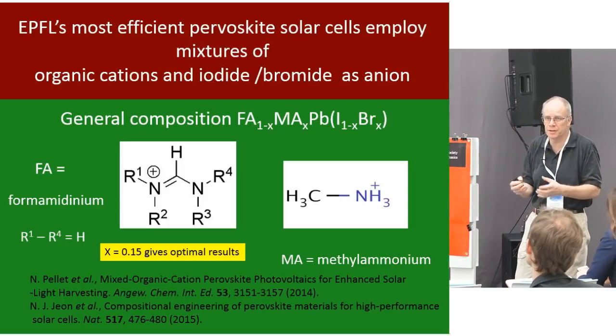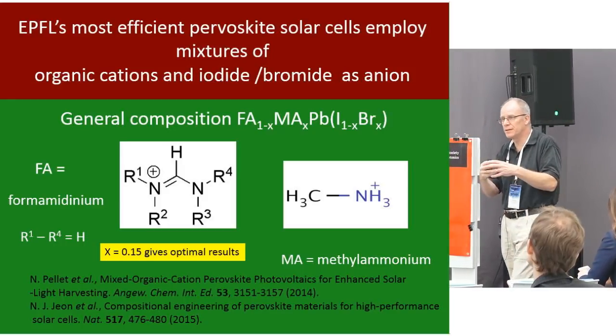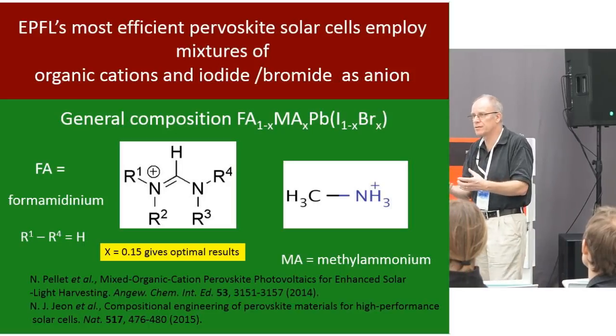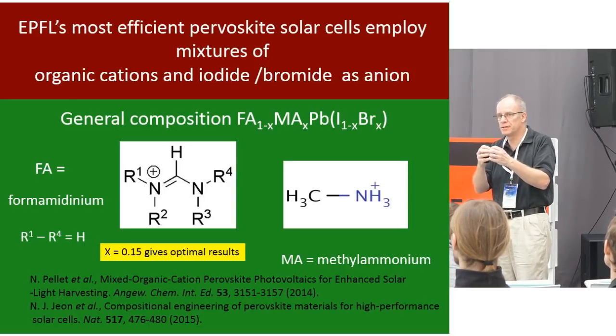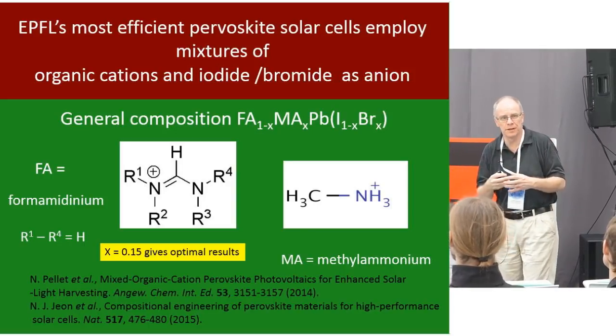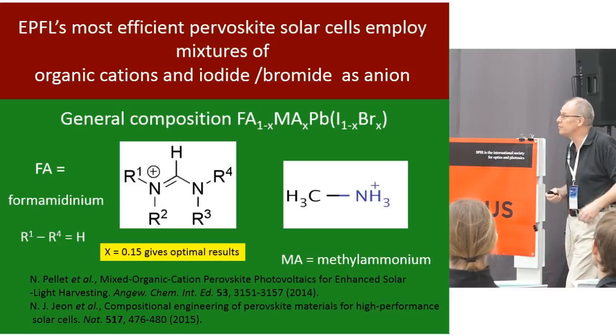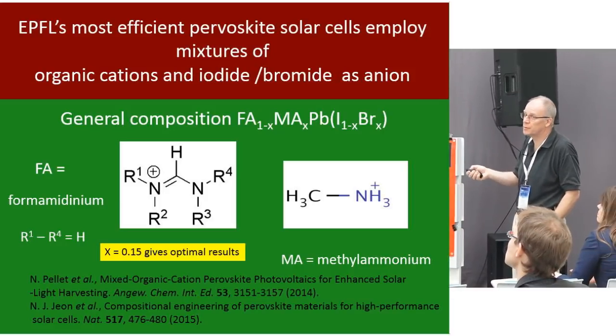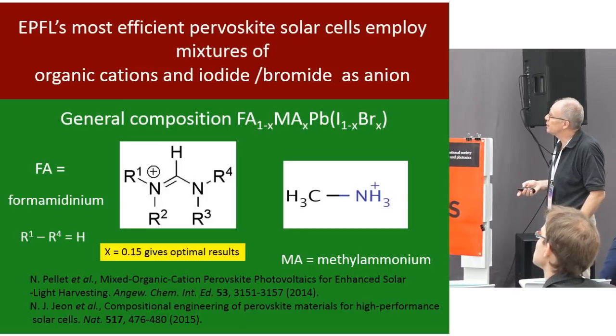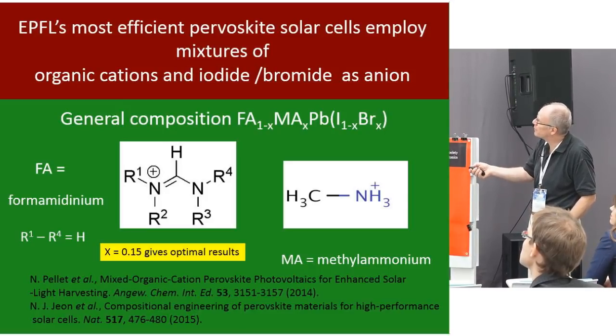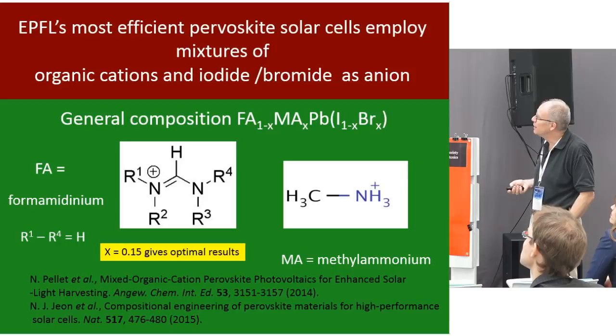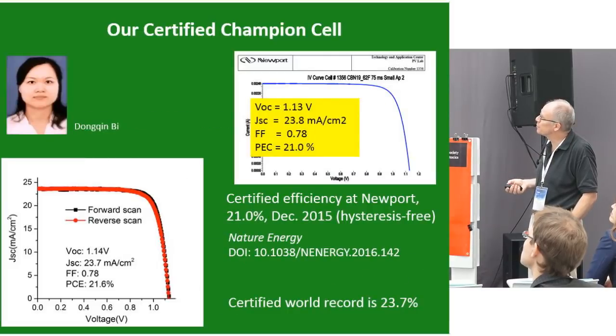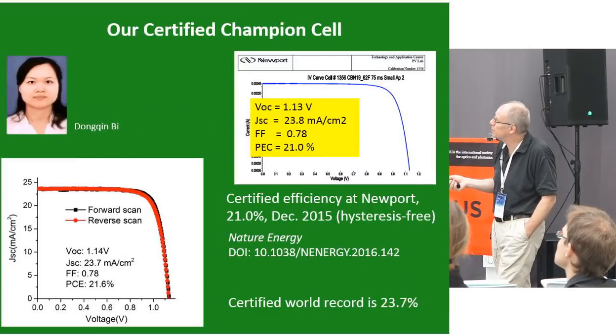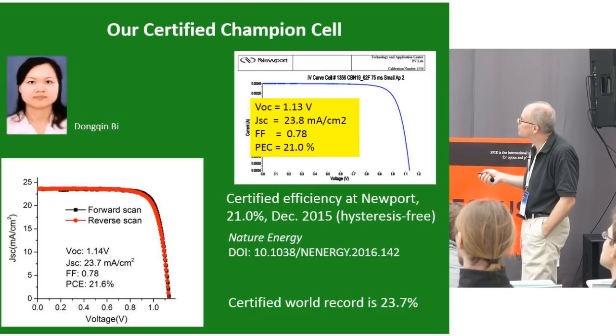So there's a lot of things going on here in terms of forming the perovskite structure and how to get good crystallites in the absorber layer and so on. So the quality of the perovskite layer depends a lot on the composition here. But with this kind of mixed, we call this the double cation, I'll come back to that, two cations. With that kind of composition, my postdoc at the time, Dongqin Bi, took the world record at 21%.